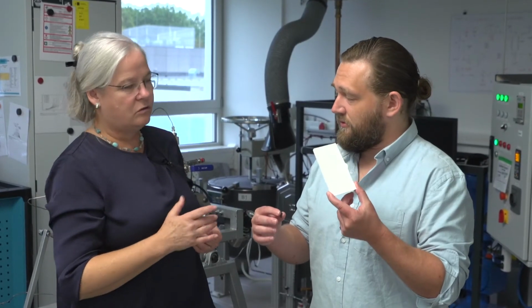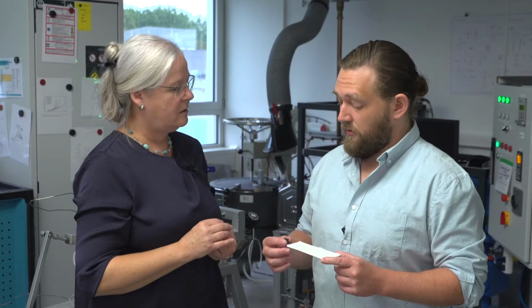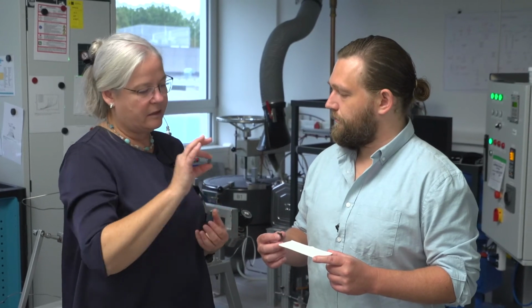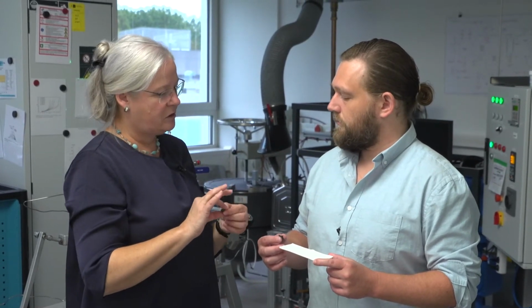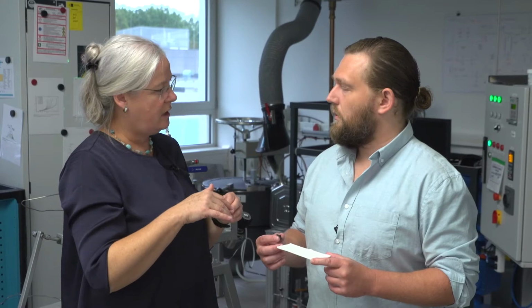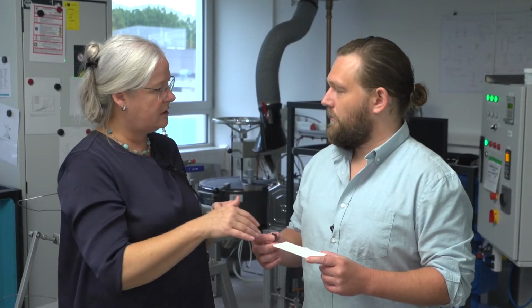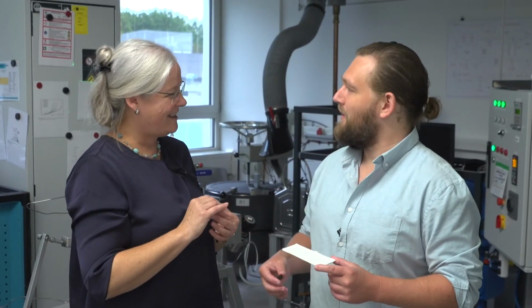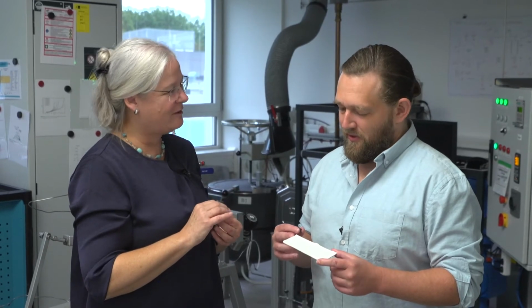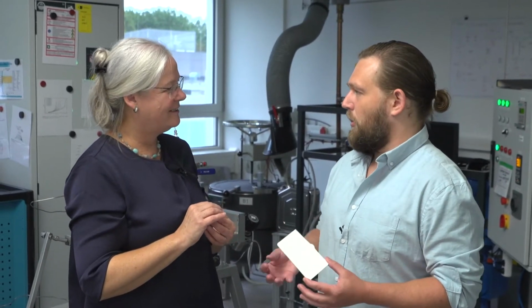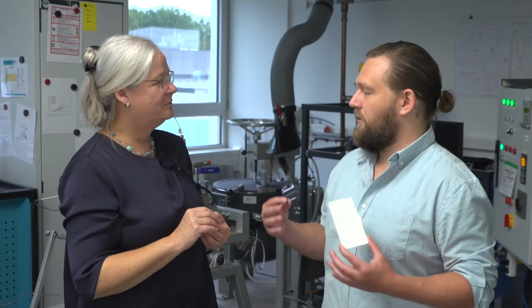So when you add the resin to this, does the material shrink? Or does it stay the same size of the aerogel? More or less the same size. Oh, that's really nice. And you can use all the normal technologies, and it is without defects because you have this nano structure and you have the capillary forces in the system. Capillarity-driven wetting. Yes, that's right. Oh, that's cool. It's a huge problem in making normal composites, eliminating voids and using vacuum technology to help push them out.